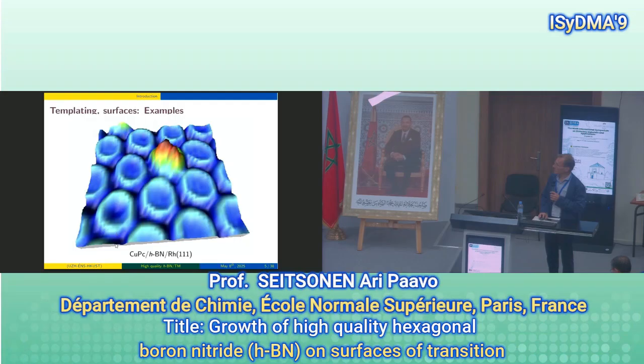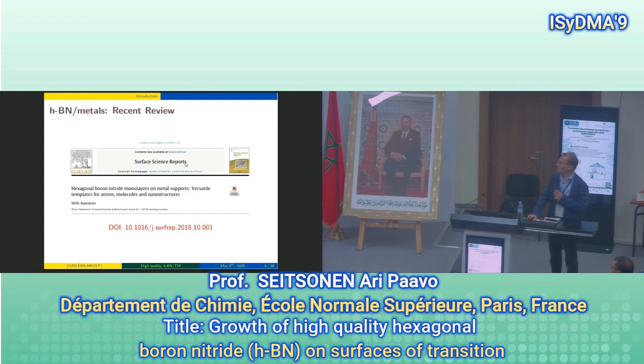And here then is an early example to try to functionalize this. So using the HBN and this larger periodicity, in this case the size of the so-called pores, these regions, is something like 2 nanometers, so some molecules match exactly in one of these pores, and the distance is something like 3 nanometers. And the idea is that using these as templates, you can selectively adsorb molecules at positions where you want, and then try to functionalize, for example, create the interaction between the molecules. So that's one of the goals also with the HBN and these moire structures.